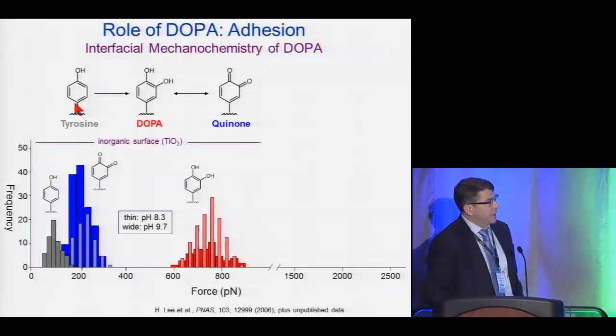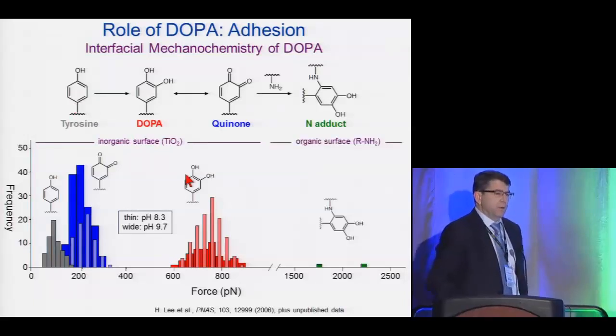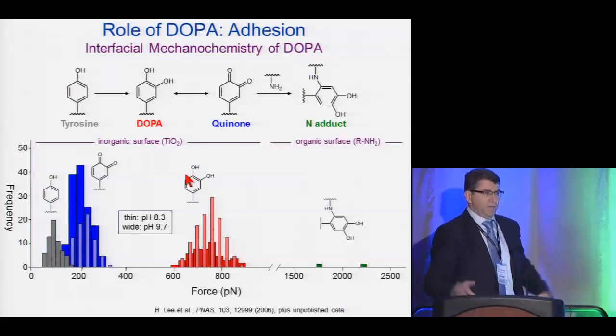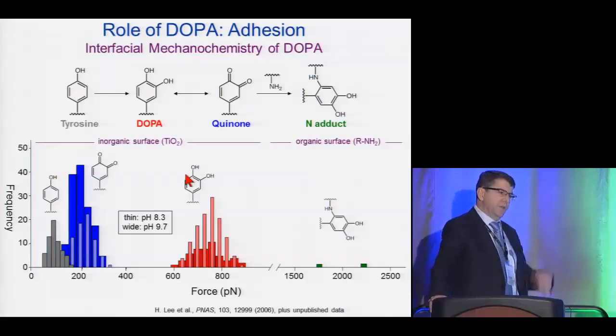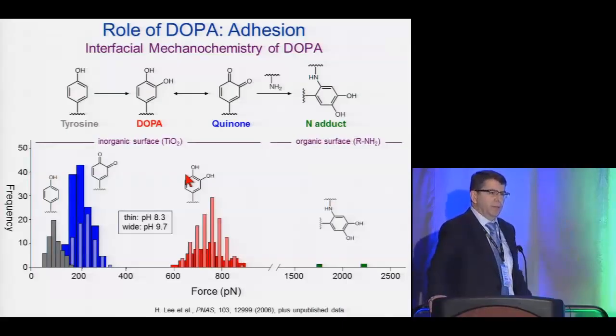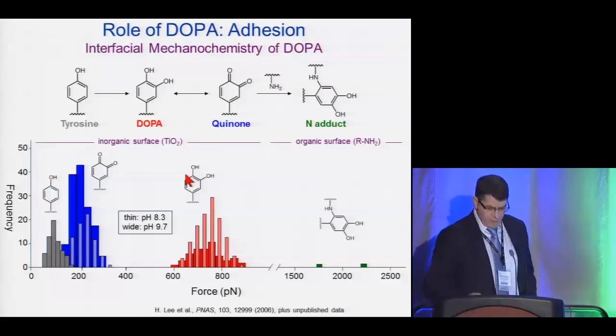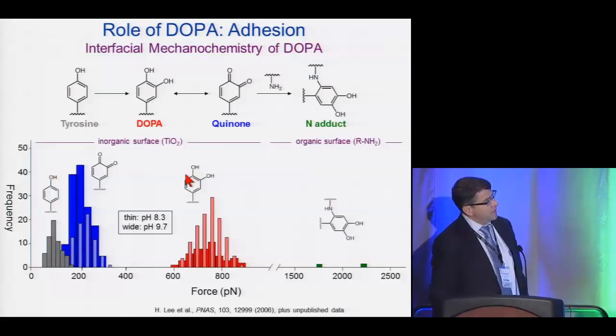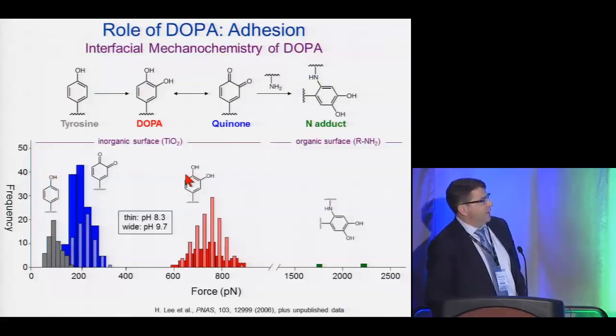Where the quinone gets interesting is when you have surfaces that are organic in nature. And of course, the mussel, when it encounters a surface, it's often a surface that, even if it's a rock, is pre-fouled with macromolecules, bacteria, algae, etc. So there are certainly organic molecules, and some may be primary amines. And under these situations, the quinone actually forms a covalent bond with primary amines. And then when we do this experiment, we pull on the cantilever, we break a covalent bond, okay? And these are the very few observations that you see out here in the 1 to 3 nanonewtons range. That's the range at which covalent bonds rupture under applied force.